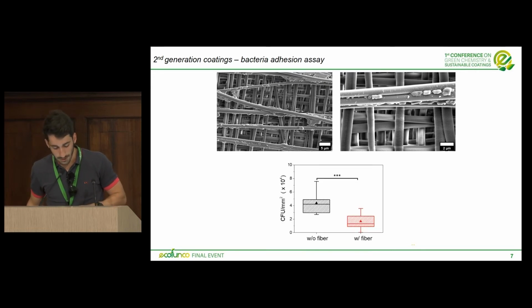Similarly as before, here we also performed the bacterial adhesion assay, this time considering Escherichia coli as bacteria, since the matrix features had dimensions of the same order as this type of bacteria. Also this time we can see that the bacteria adhere at the top of the surface, and we did not observe penetration through the surface. The numerical results confirmed what we have seen by the SEM images. So there is a reduction with the coating, and there is also a statistical difference. And we have calculated that the reduction of bacterial adhesion was about 69%.